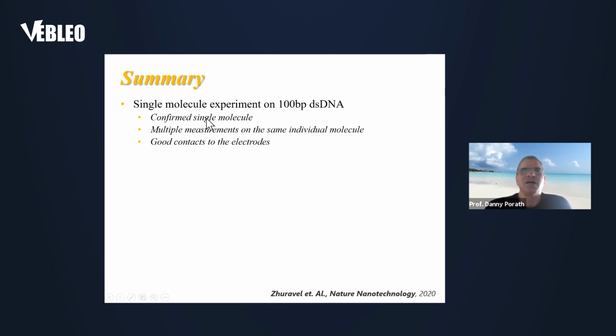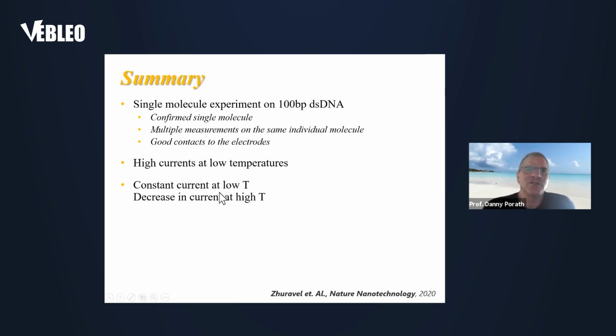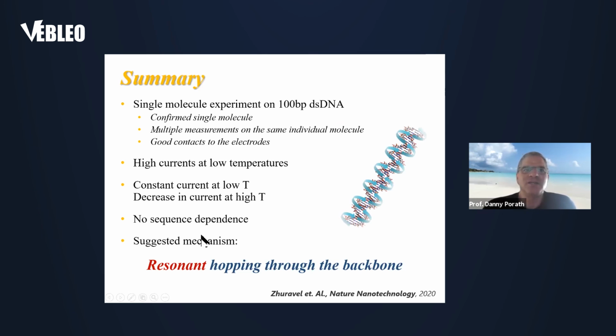So to summarize, a single molecule experiment on 100 bases, that means 30 nanometer long double-stranded DNA, confirmed that there is a single molecule, and we could measure again and again the same molecule that had good contacts to the electrodes. We had high current at low temperatures and constant current that decreased with the temperature above 50 degrees. We did not observe a sequence dependence, and that suggested after the measurements with the nicked DNA that resonant hopping through the backbone might be the transport mechanism.